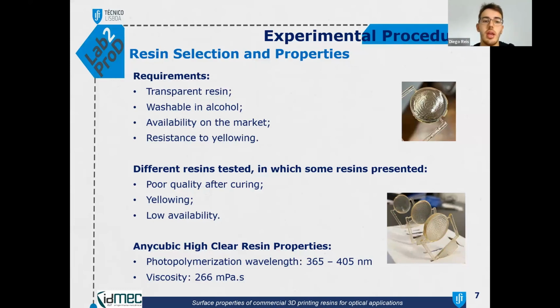Mainly the transparent ones. We tested different resins, but some of them presented poor quality of the cure of the coating. One example of this is shown in the first image, where you can see that some patterns were formed. This is due to different gradients of UV light absorption. Some of them also presented yellowing, and some resins had low availability because manufacturers discontinued them. So this is one of the requirements that we selected, to have a good availability on the market so you can continue to study it. The best one that we could find was Anycubic High Clear resin, with the following properties.